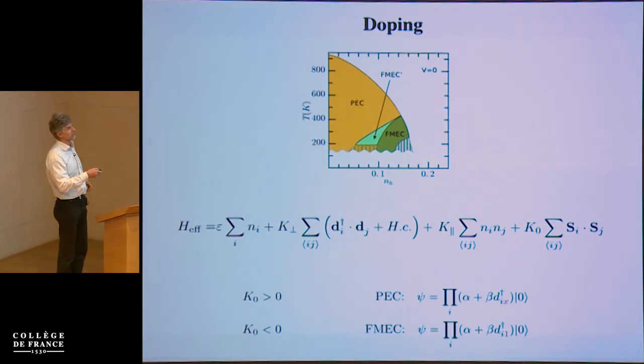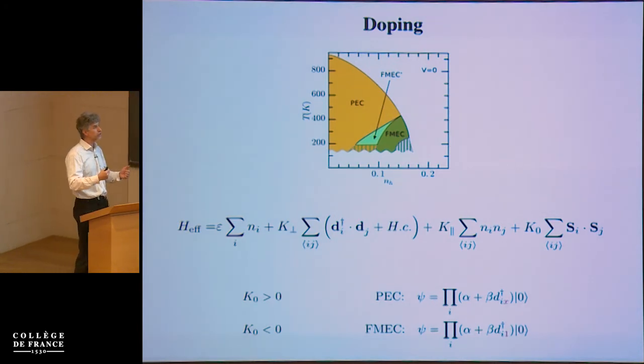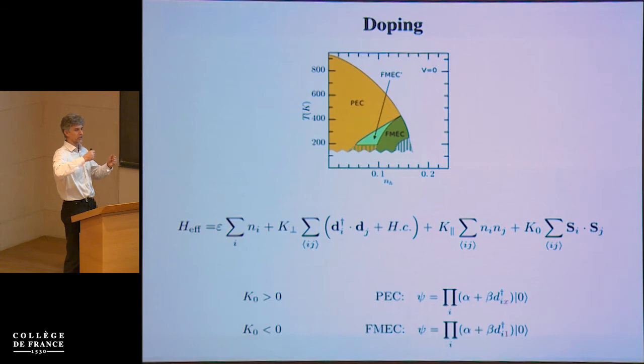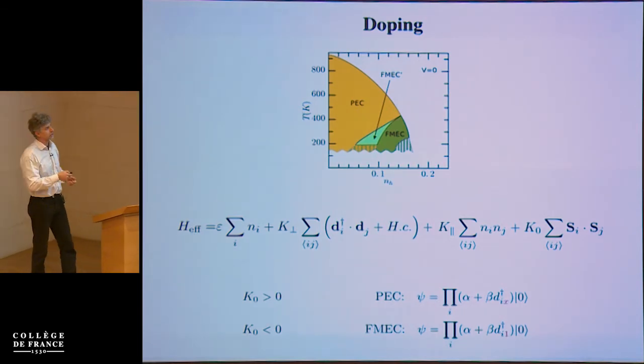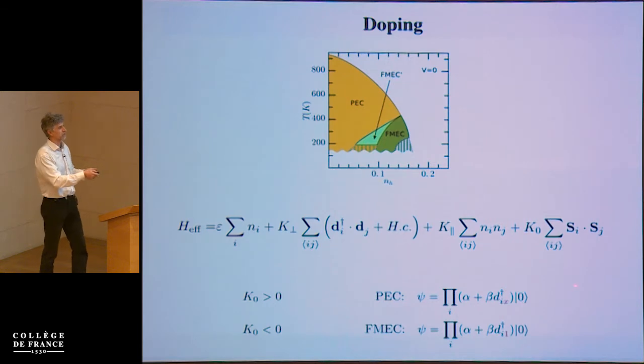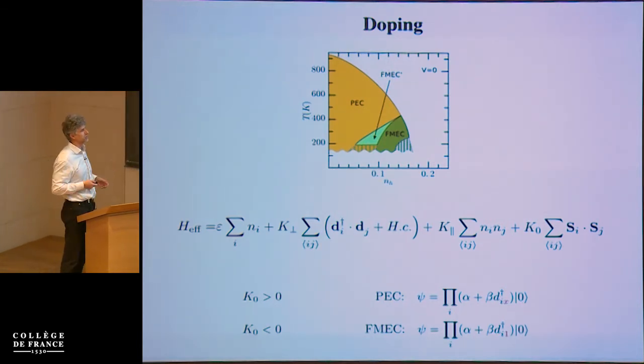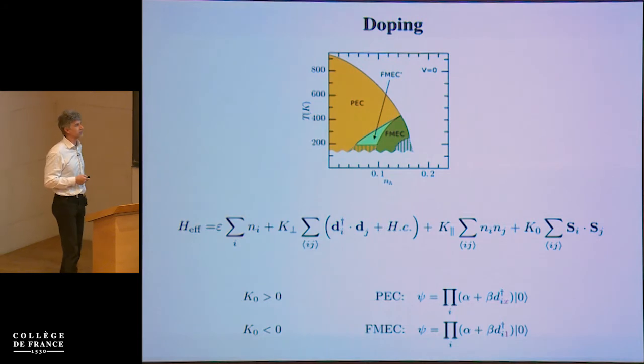But to understand the phase diagram, it's actually enough to realize that what the doping does is it changes the sign of this spin-spin coupling. So in the normal phase, or in the undoped phase, we have an insulator where the antiferromagnetic super exchange dominates, and if this K0 is positive, the order parameter, we get this polar condensate where the boson that condenses has this kind of form that it has some direction in the Cartesian representation. Let me put it this way: simply, it does not carry any magnetic moment.